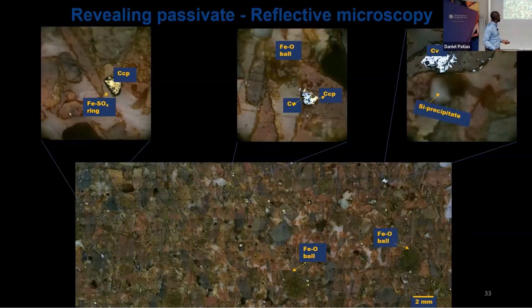So in picking points of interest, in one of the cases for the fines, this is what we had. With larger surface area, we flow in from this direction, from left to right. We observe clearly ferric oxide balls - these were in there before we started the experiment. And if we pick specific regions of interest, you could see ferric sulfide ring and then chalcopyrite. And if you zoom in on other sides, you have covellite, where your chalcopyrite is actually transforming to covellite, and you have more ferric oxide balls.